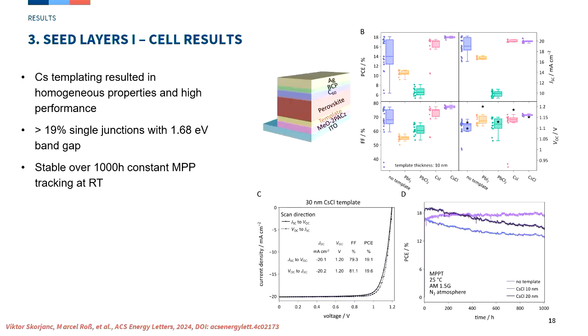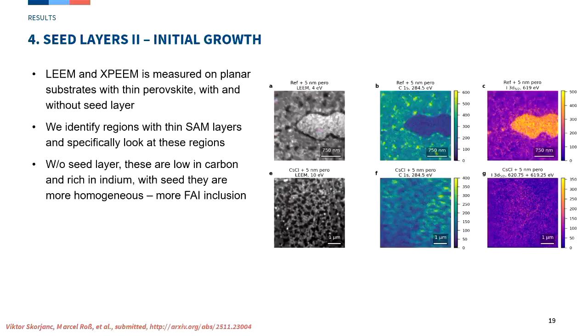In Berlin we have a synchrotron, which provides very nice measurement opportunities, so we used it to try to understand the initial growth better. What you see here now is microscopy, microscopic elemental resolution of the very first growth, the very first nanometers of the perovskite.